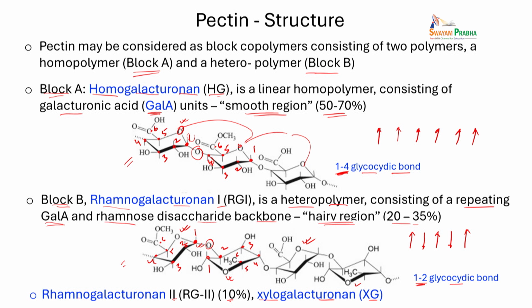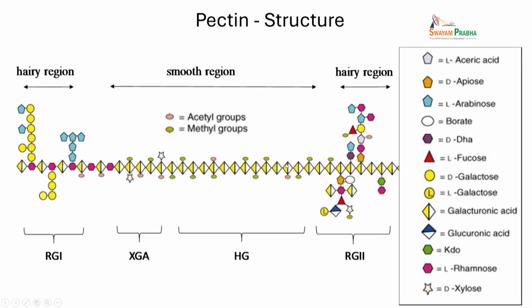Depending upon where you extract pectin from and which method you are using to extract, you may have a compositional variation between homogalacturonan, rhamnogalacturonan 1 and 2, and then xylogalacturonan. Okay, and that's what makes it a little bit difficult to study and reproduce pectin-based material. I think I have a kind of geometric model of this pectin.